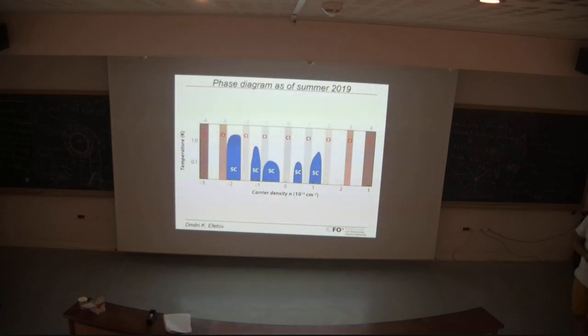And actually, 2 weeks ago, there were again three papers published on STM results. Last time I also touched base on STM results. STM results are also local probes, so they can locally, in the cleanest region of the device, measure similar types of gate dependencies. They can measure the spectra as a function of carrier density, and they now all observe these gaps at other integer fillings. But unfortunately, they cannot yet really confirm the correlated insulator states. STM hasn't gone yet to the lowest temperatures, so superconductivity has not yet been studied with STM. But this will come soon.